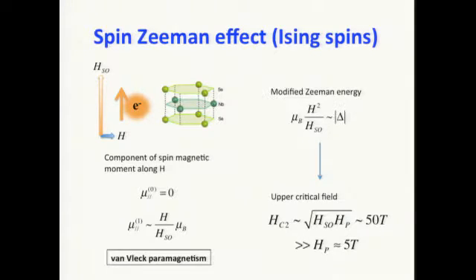You can work out the math a little bit, and it turns out that now it gives rise to a modified H_c2, the upper critical field, which is a geometric mean of the spin-orbit field and H_P. So it's significantly bigger than H_P if we put H_SO at about 500 Tesla. That gives rise to 50 Tesla of upper critical field.